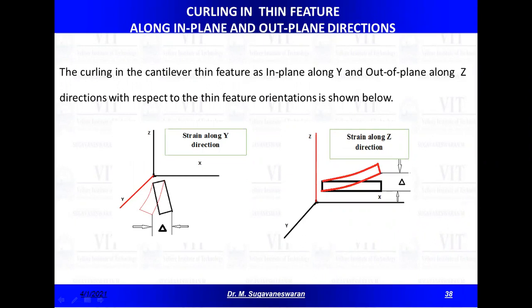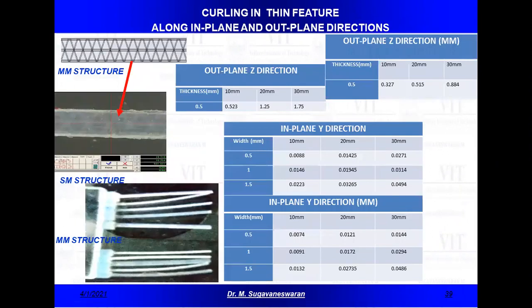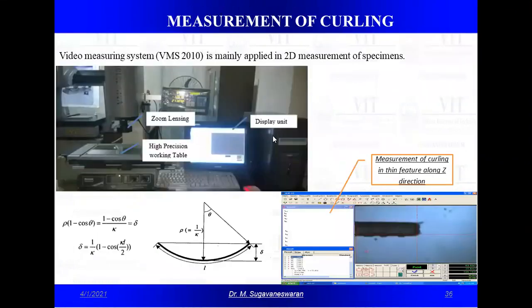As we have a specific property, as we are designing the material with a specific orientation, in the comparison between the multi-material structures, though it is not an optimized one, we have taken the quasi-isotropic directly. It is not varied because at the bottom the Young's modulus is different from the top. So if we look into the curling behavior of the thin feature, though it is not an optimized condition, the quasi-isotropic has high resistance to bending at the top and bottommost layers. That is what we observed even in finite element analysis.